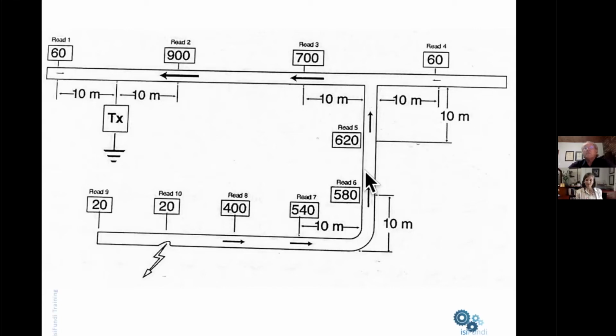So maybe this was a pipeline along a road, and the branch goes under the road and off through a factory development on the other side. And you can follow that pipe and follow it through. And if you come here, and this defect effectively could well be, say, a non-functional insulating flange on a gas distribution network where the pipe goes into an end user. And you could say, oh, okay, that's where I need to go and do my maintenance work in order to repair the system so that my cathodic protection system can function as it should. So it's a really, really powerful investigative tool. And for me personally, that is my preference. If you are trying to find a problem, then this is the system to use.